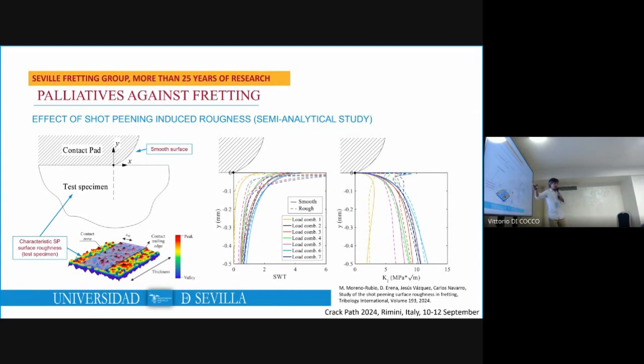Very close to the surface, the cases having the typical surface roughness of shot peening produce higher values when compared with the smooth cases. But below the surface, the important thing here is that we can observe an important decrease of the Smith-Watson-Topper parameter or the mode 1 stress intensity factor. So this result can explain why the characteristic surface roughness produced by shot peening can be used as a palliative against fretting.